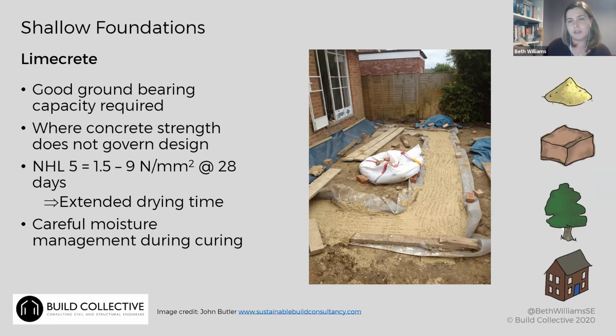An NHL 5 mix might give you between 1.5 and 9 newtons per millimetre squared capacity, depending on the mix. And the hardening and the design strength can be significantly altered by the amount of water that gets into the mix during curing. So you need to be very careful whilst it's curing that it's protected and that you leave it for long enough that it can reach its design strength. But other than that, it is an option on some sites.